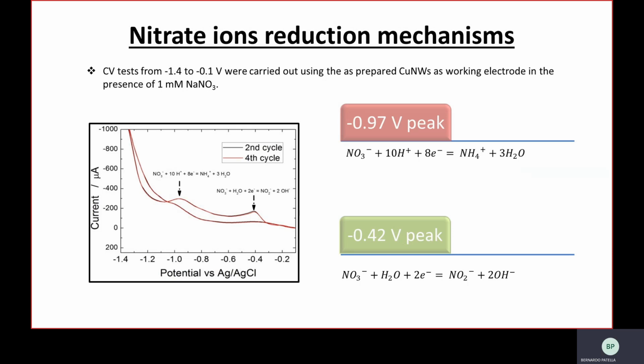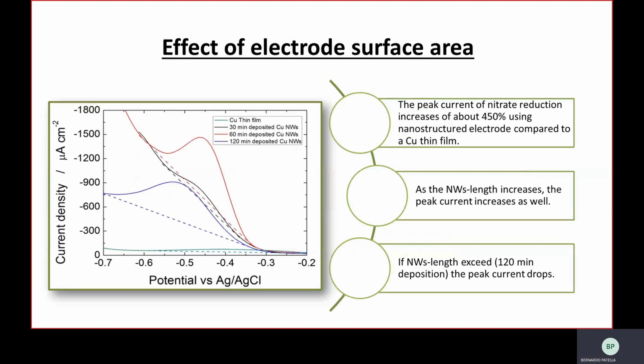Considering the higher intensity of the peak located at minus 0.4 volt, it has been selected to calibrate the sensor. This slide shows the influence of the surface area. A thin film of copper produces a bell-shaped and low-intense peak, while a nanowires electrode obtained after 30 minutes of deposition shows a much more intense peak.